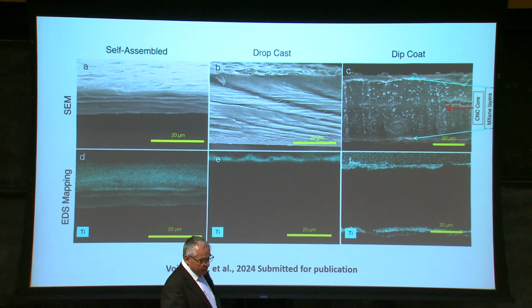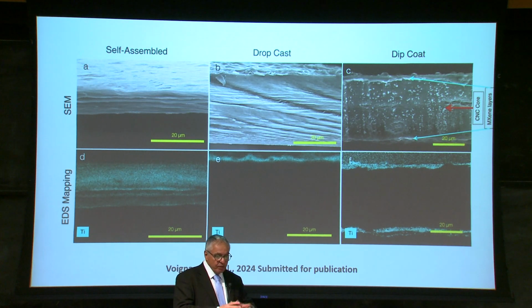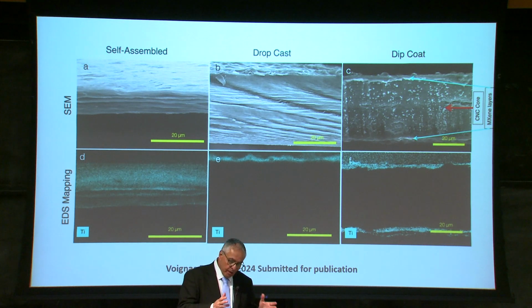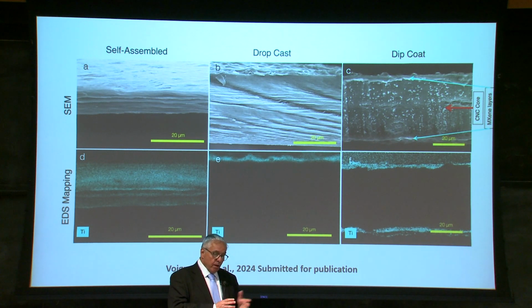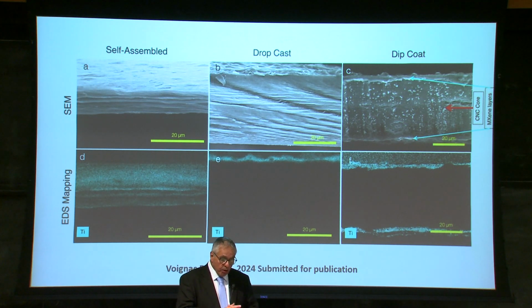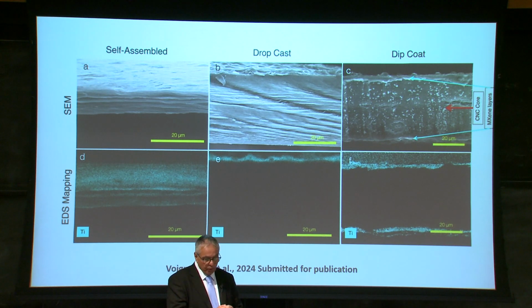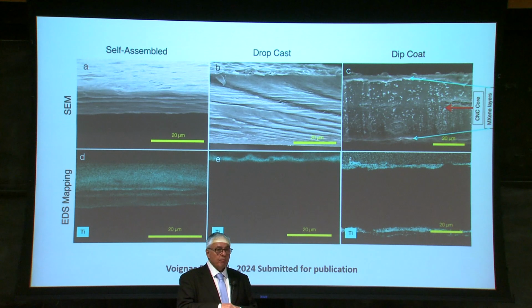So you can see on the left-hand side at the top, this is self-assembled CNC cross-section in the SEM. You can see the layers. And when you do EDS mapping, you can really see that the MXene is everywhere. When you do drop casting, it's only from the top. Again, in the middle, panel B, you can see the nice organization of the nanocellulose, but the MXene is only at the top. And when you do dip casting, this is the right panel, you can see actually that the MXene stays only on the surface, it doesn't penetrate inside.